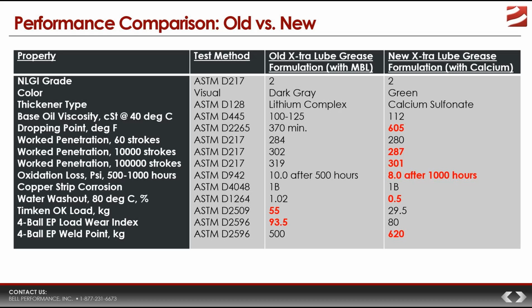For the test itself, they take a grease sample and put it in a pressurized oxygen chamber filled with oxygen at a given pressure, a given PSI. Since it's a sealed chamber, you know there's a finite amount of oxygen in that chamber. They raise the temperature and let the grease sit there and oxidize or react with the oxygen for a certain amount of time.